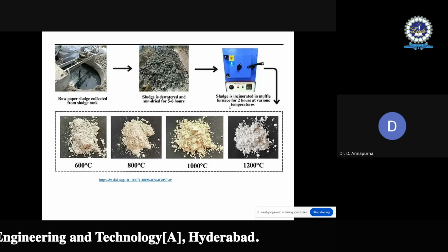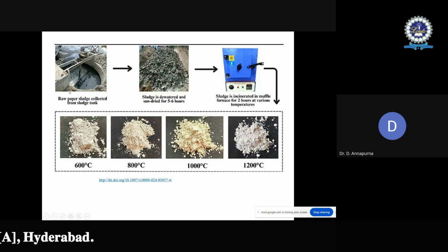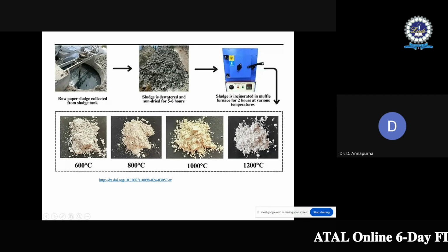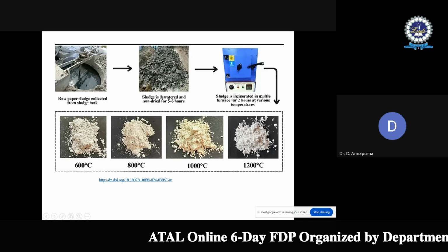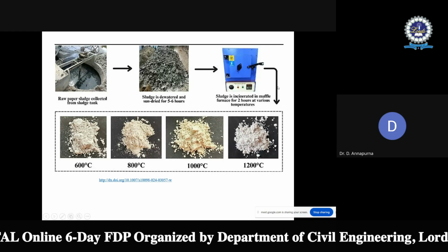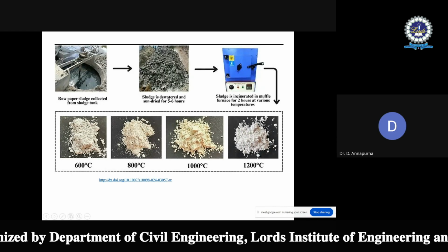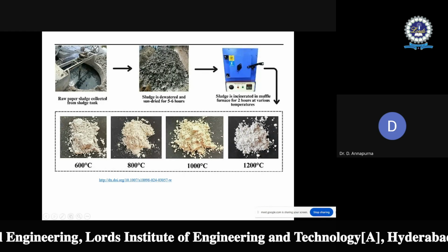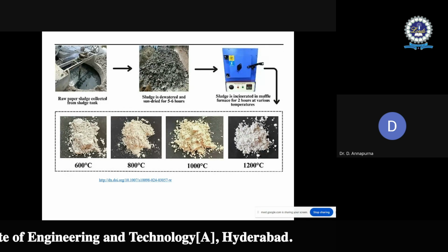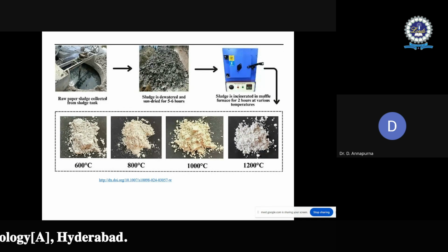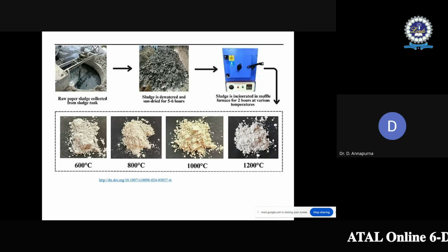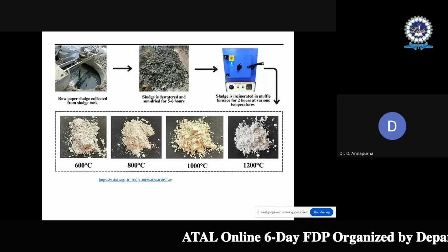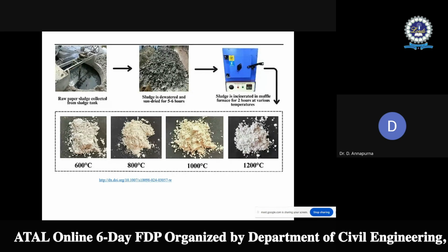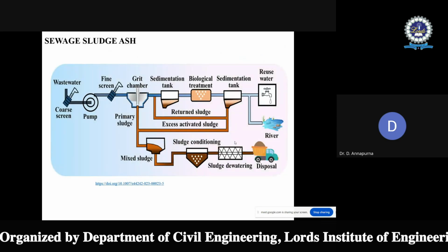In the paper industries, the raw paper sludge is collected from the sludge tank, then the sludge is dewatered and sun-dried for 5 to 6 hours. Then it is incinerated in the muffle furnace for 2 hours at different temperatures, and further it is sieved to get the paper sludge ash. It is again rich in calcium, silica, and alumina. So it can be used as a source material and also as an admixture to the geopolymer concrete. Then the next one will be the sewage sludge ash.